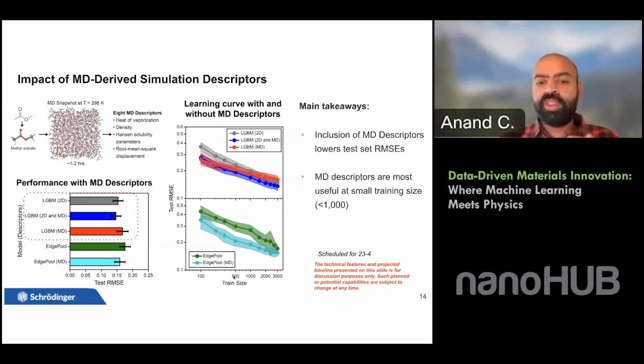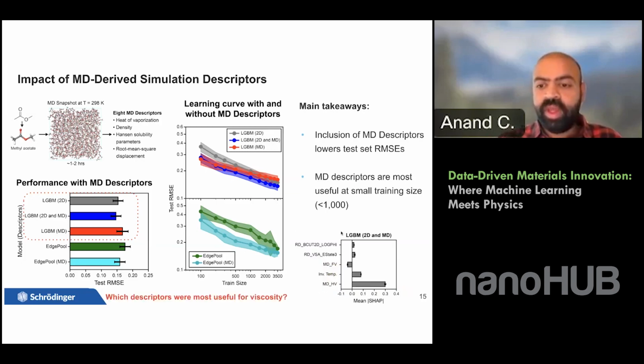And the biggest problem in material science, especially amongst most of our customers, is that they are dealing with small data set sizes. So having the power of really powerful descriptors from physics-based simulations can really reduce the amount of data that we need for machine learning. And using the Shapley feature analysis, we looked at the most important descriptors for viscosity. And we were able to show that, for example, the heat of vaporization obtained from MD was the most important descriptor for viscosity, and it was positively correlated with viscosity as well.